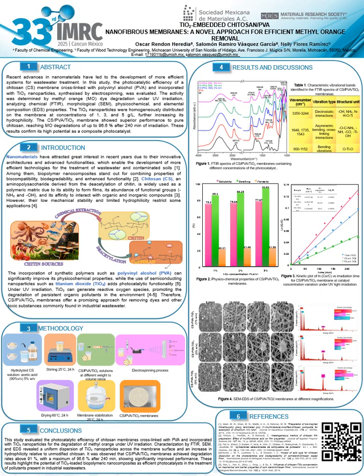About the photocatalytic degradation, methyl orange showed a direct relationship between titanium dioxide content and degradation efficiency. Pure chitosan PVA membranes display only minor adsorption of the dye, whereas the 1% titanium dioxide membrane reached approximately 17.5% degradation in 240 minutes. Increasing the titanium dioxide content to 3% improved the removal efficiency to 91%, while the 5% titanium dioxide membrane achieved 96.6% degradation under the same conditions.